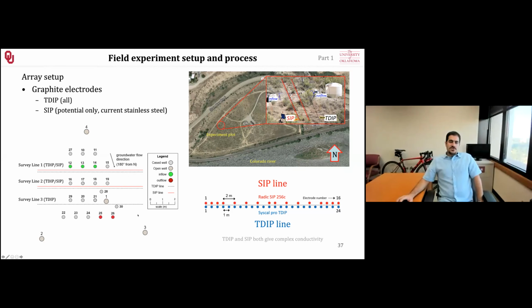Anyway, we had our SIP measurements at two lines, close to injection and in the middle, and we assumed, because by now everything was precipitated, that we didn't need a third line here at all. But because time domain measurements of IP and resistivity are faster, we did three. One close to the injection port, one in the middle, and one close to the withdrawal port, to make sure we map everything. We have a 3D grid sort of thing to map everything that is occurring in the subsurface here.